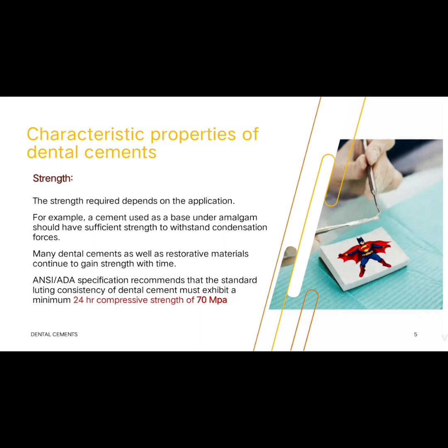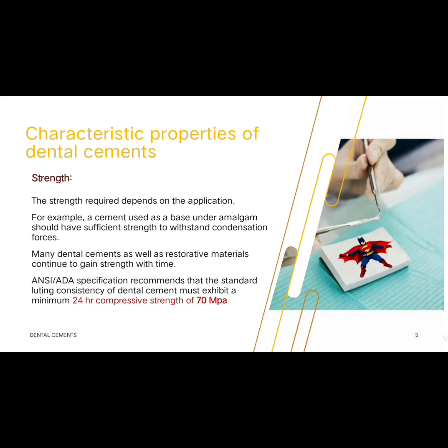It is said that many dental cements as well as restorative materials continue to gain strength over a period of time. Now this is very important for your NEET purpose, that is, the standard luting consistency of dental cement must exhibit a minimum 24-hour compressive strength of 70 MPa. Remember this, very important.